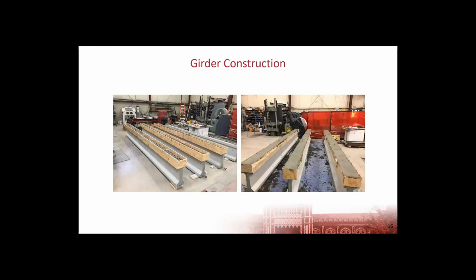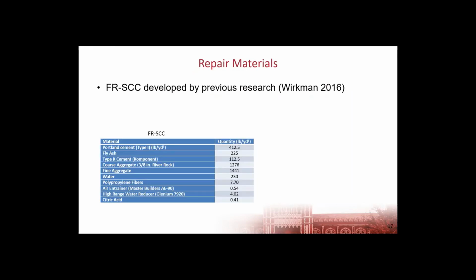So once we had the specimens constructed, we were going to test those to failure in shear and then repair them using these three different repair materials. The FR-SCC that we used was developed through previous research at OU. Former student Corey Wirkman back in 2016 did the initial work on this, but it also built on work of my colleague, Dr. Jeff Voles from Missouri S&T originally.